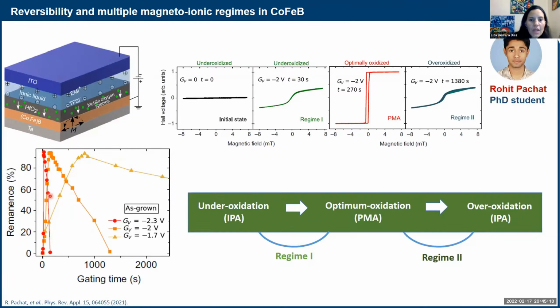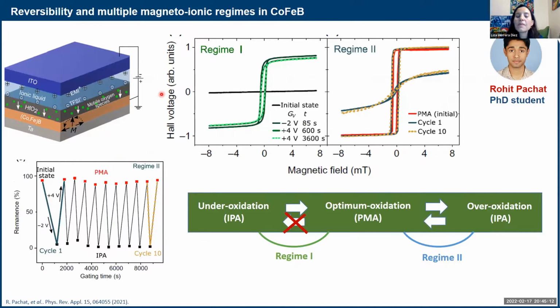So we went there and measured reversibility. In regime 1, within the window of gate voltages that we can use with the ionic liquid, we couldn't reverse this state. I mean, of course, it doesn't mean that it's completely not reversible. It's just not within the window of voltages that we have. However, regime 2 was very much reversible. So here you can go from PMA to in-plane over-oxidized and back and forth. And here we did it about 10 times. So it really goes back and forth very nicely.